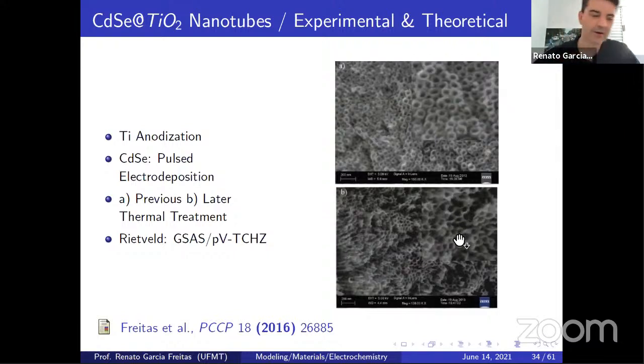It's not quite simple. Oh, come on, professor, it's quite simple. You just do that in physical chemistry experimental. During the undergraduate, I put the electrode, apply an electric field, and the cations go there and deposit on the surface. But not so. If you remember, titanium is a conductor, but titanium oxide is not. Titanium oxide is a semiconductor, a very, very special kind of material. But in dark condition, it's a dielectric. Depositing on titanium is one thing. Depositing on titanium oxide in dark condition is quite different, because titanium is a conductor, but titanium oxide is a dielectric, it's an oxide. So we have a decrease of the voltage.